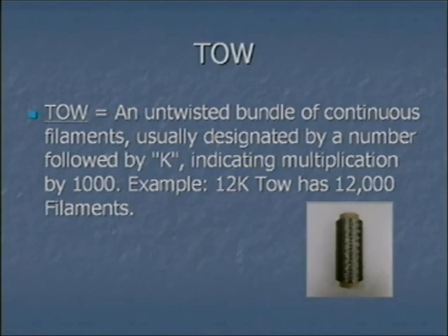So when you're purchasing carbon fiber, you'll find some manufacturers have very heavyweight carbon fiber braid or lightweight, and that's a result of the different types of tow, or the K value of the tow that they're using to produce the braid or the sheet material. So they can get different thicknesses in the tow.